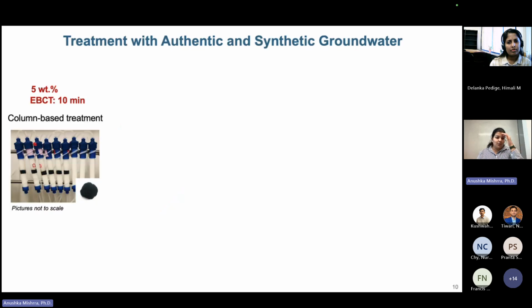To do this, we did a lot of column-based experiments to mimic real-time filtration systems that are out there. These are usually for activated carbons, but you also have ion exchange columns. All these columns have a contact time, and typical contact time ranges from 5 to 10 minutes, so we went with 10 minutes.